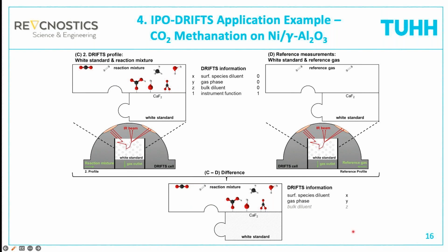And now we open the drift cell and exchange the catalyst by the pure diluent, by calcium fluoride, and then we perform the same set of measurements. And now you see we have, if we expose it to the reaction mixture from the CPR, the surface species on the diluent, we have the changing gas phase, and we have maybe changes in the bulk diluent, and we have the instrument function. If we do it in the reference gas hydrogen, this is fixed, and the instrument function is, of course, ideally the same as in the left experiment. So if we calculate the difference, we are left with the surface species on the diluent, the changing gas phase, and maybe changes in the bulk diluent, but this is very unlikely because calcium fluoride is very inert.